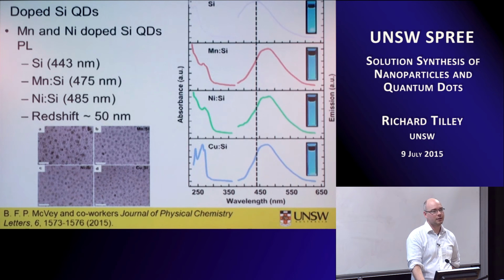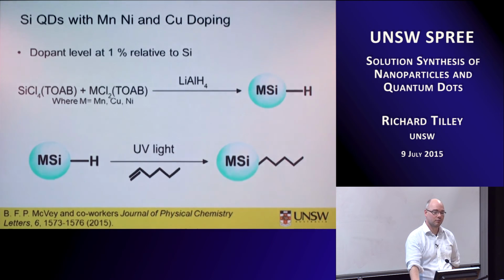So if there are any suggestions, we could very happily go away and try and put different conducting molecules onto the surface. The ones we've mainly focused on so far have been groups that will make the dots water soluble, and functional groups which aren't going to be too reactive. So the types of functionalities we've put on have been things like alcohols or amines so far. But we can easily put on longer or shorter molecules, or molecules which, say, have some double bonds which might be conducting, for example.